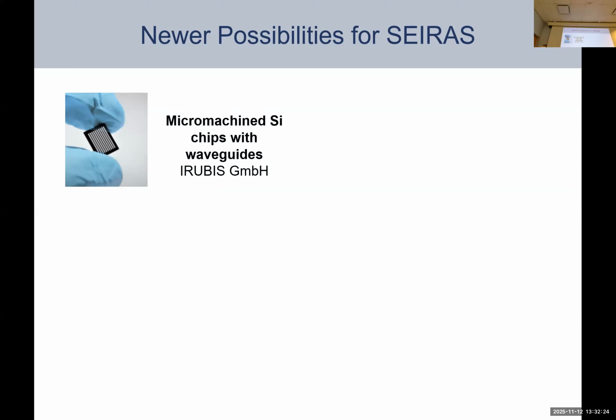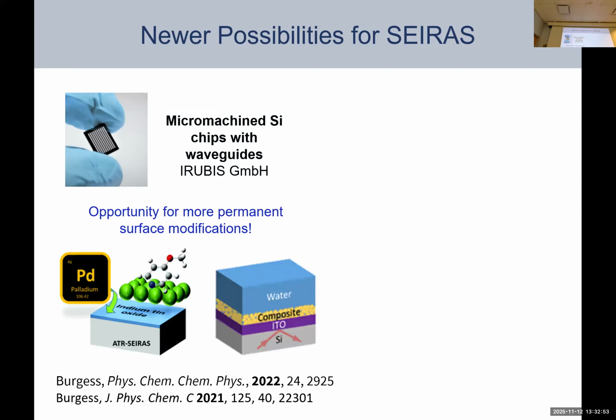So what's nice about this is that these chips now allow you multiple sort of passes of your IR light through the chip. And we can now sort of decrease the size, giving you rise to this nice little chip. That means that we can start coating these with materials that are perhaps difficult to remove off of silicon, very strongly adhering. It's hard to clean these, and so you can essentially make an electrode and use it until it's no longer good and then throw it away.